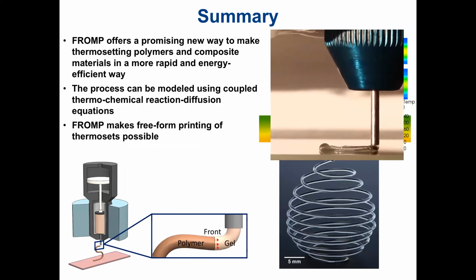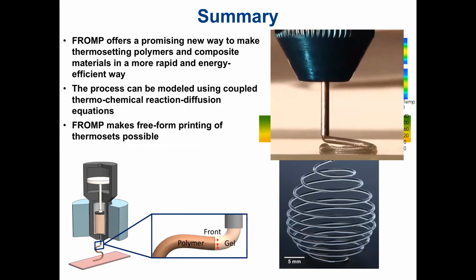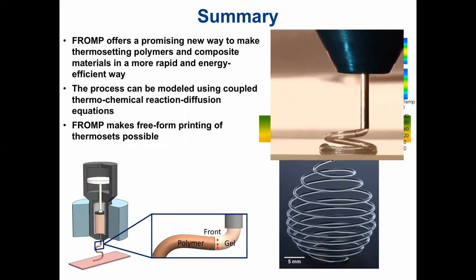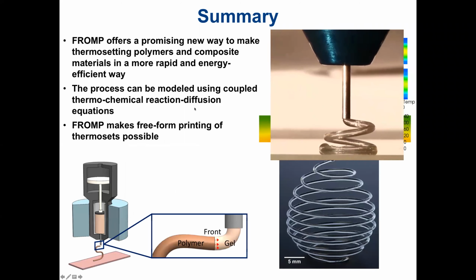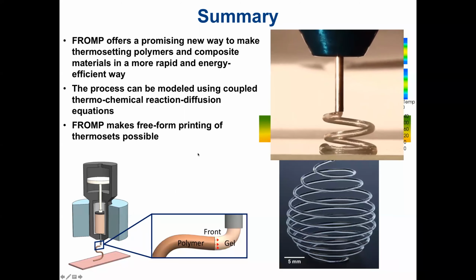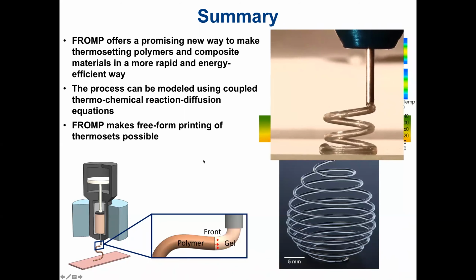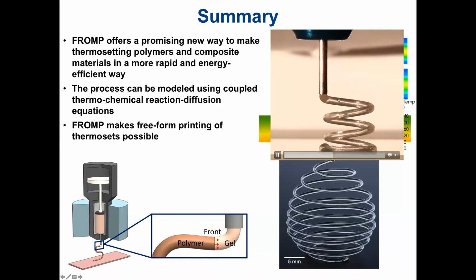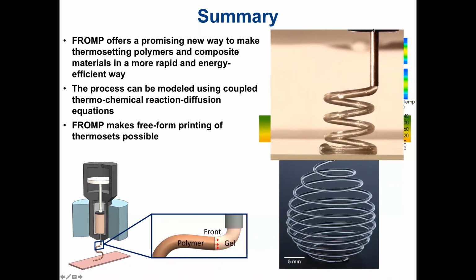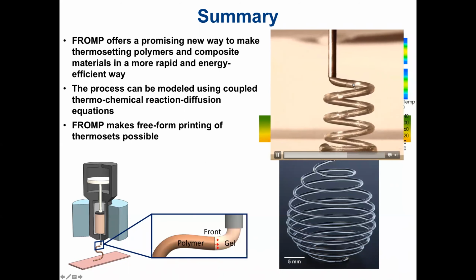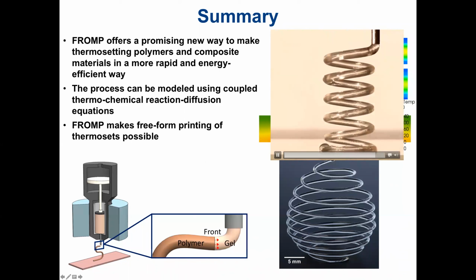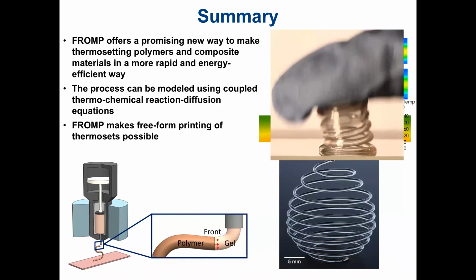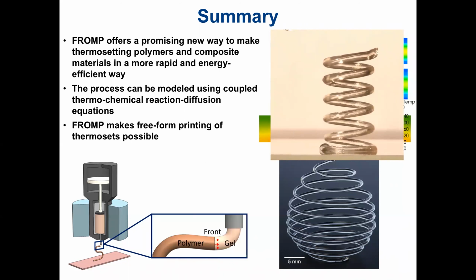Another thing, and I didn't have time to talk about it, but this is a whole new area where we believe frontal polymerization could play a very important role, is in 3D printing. So this method allows us to really make free-form, three-dimensional features, such as the one you can see in the animation. We deposit here a DCPD gel, and as soon as you deposit it, you have the front that follows the needle, and we can actually make, using this technique, a material that is polymerized right on the spot, and we can make different types of shapes.